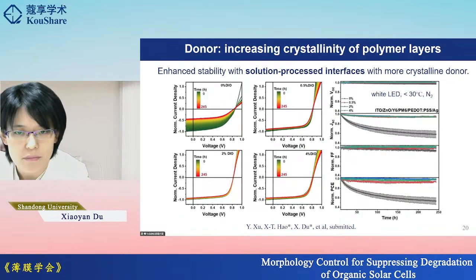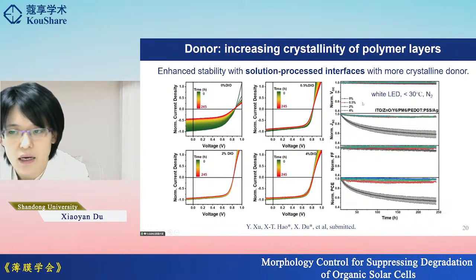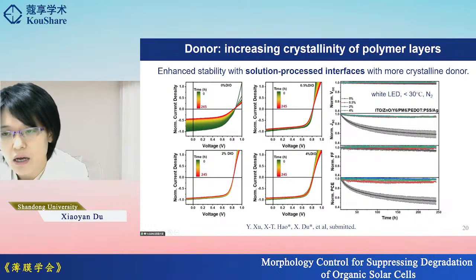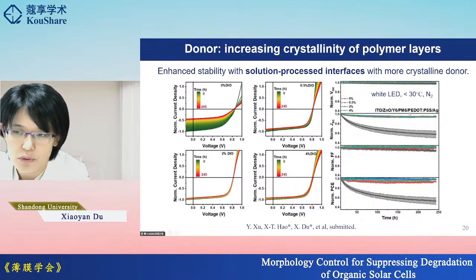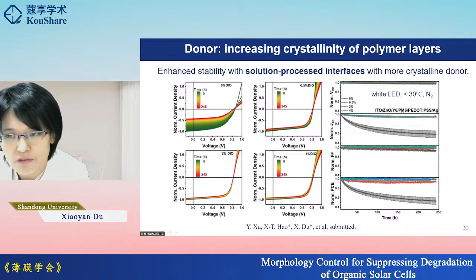In addition, we also show that this interface with the solution processed hole transporting layers, here we use PEDOT:PSS, is also very important to the photostability here. So the device with very amorphous polymer layers here shows a very fast decrease in the photocurrent, and with the enhanced crystallinity, we see significantly enhanced photostability.